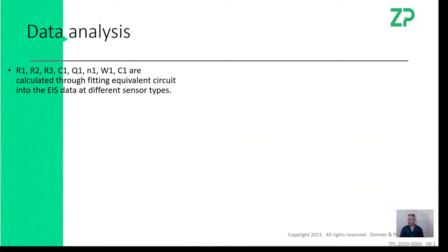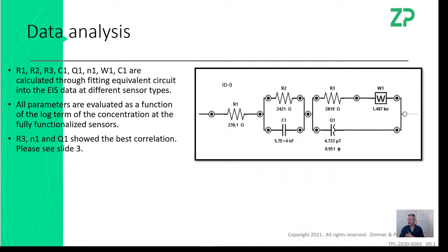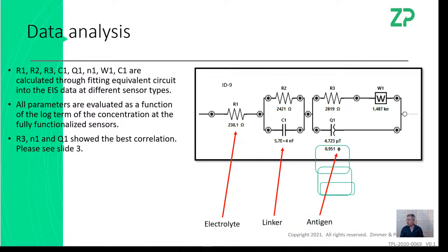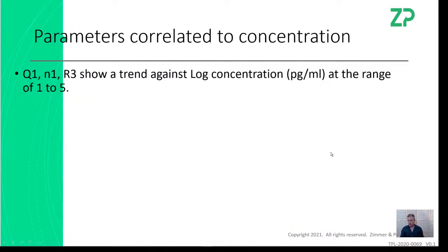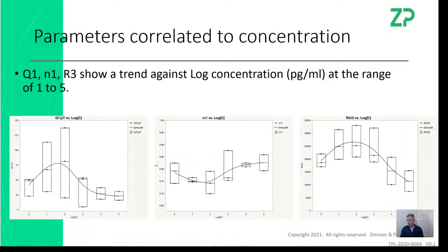And then we actually do the data analysis itself, which we do by EIS. Now it's probably worth saying that we sometimes have to use quite complicated maths to do this. So, we make an equivalent circuit. We don't use R1 because R1 just tells us about the electrolyte. But we often are interested in C1, but the antigen in our experience is often associated with Q1, R3, and this angle here. So we end up in our study sometimes actually using all of these components that we combine.